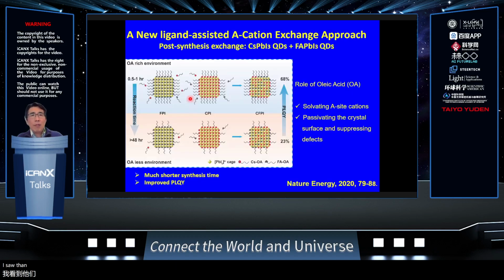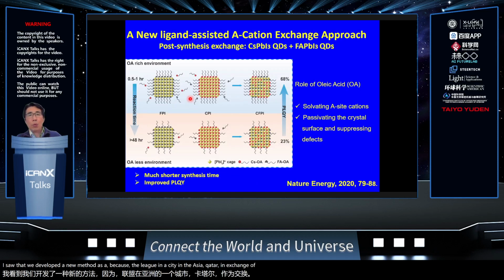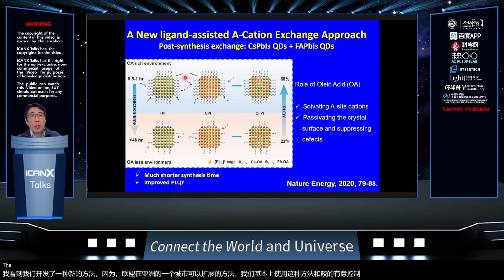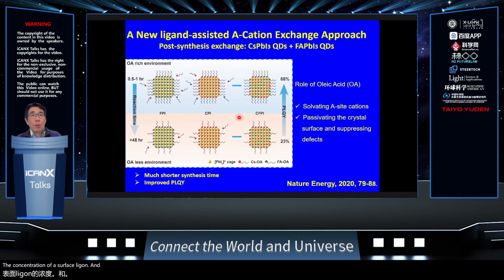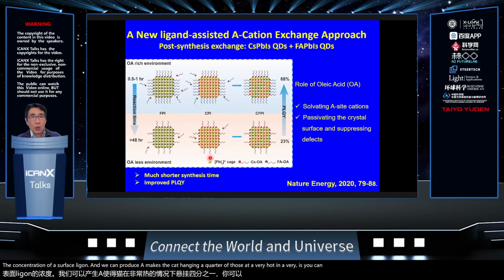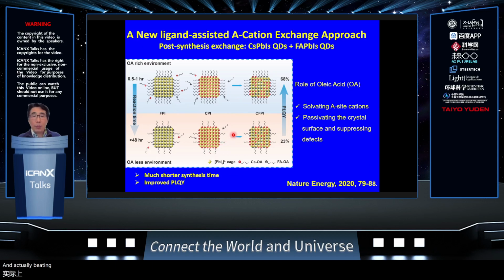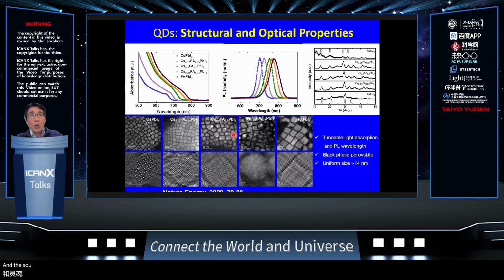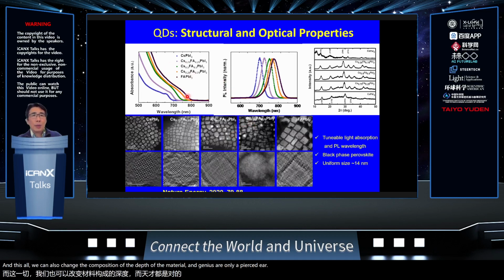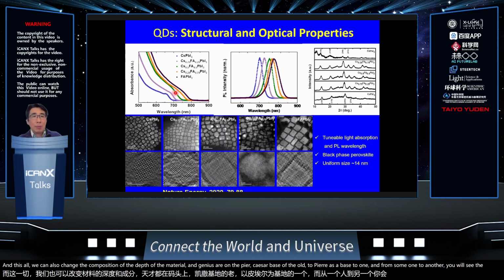And so we developed a new method, the ligand-assisted A-site cation exchange approach. Using this approach, by intentionally controlling the concentration of the surface ligand, we can produce mixed cation quantum dots in a very short time window, and they also have very good quality in terms of PLQY. We can also tune the composition of the material from Cesium-based to FA-based. From one to another, you will see the band gap change and the color change.